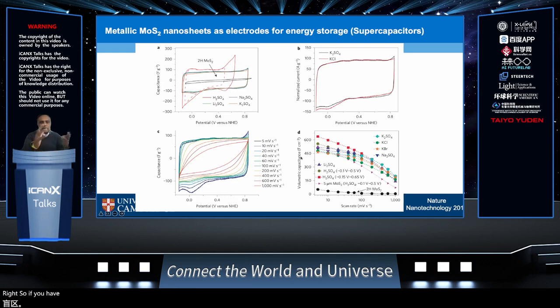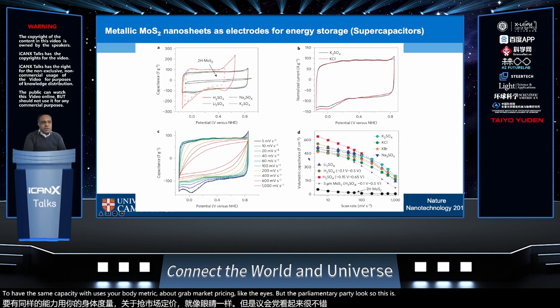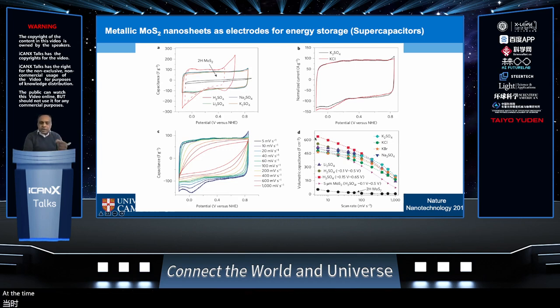So if you have large surface area electrodes, then you need lots of volume to have the same capacity, which reduces your volumetric capacity. Your gravimetric capacity might be high, but the volumetric capacity is low. So this was a little bit different at the time because we were not relying on the high surface area for capacity. Instead, we're relying on the efficiency of the intercalation and deintercalation process. And we did XRD to show that there's an expansion of the spacing between the nanosheets